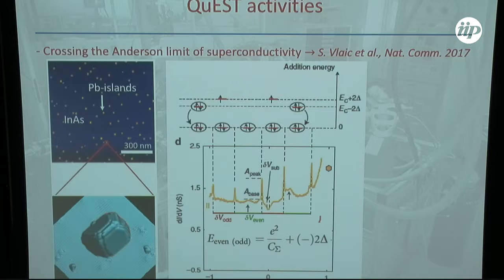And one paper that could be interesting also for people doing superconductivity is a demonstration of the so-called Anderson limit in superconductivity, when the size of the superconductor becomes so small that the mean level spacing of electronic states becomes comparable to the gap that could be in this material, and the superconductivity vanishes. This was a conjecture of P.W. Anderson, and we experimentally realized it.